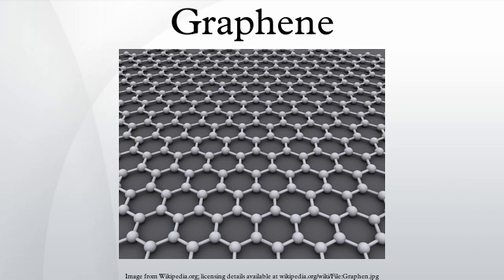Analysis of SLGO generated by this route reveals that the system is unstable, and room temperature stirring with HCl leads to around 60% loss of COOH functionality. Room temperature treatment of SLGO with carbodiimides leads to the collapse of the individual sheets into star-like clusters that exhibited poor subsequent reactivity with amines. It is apparent that conventional chemical treatment of carboxylic groups on SLGO generates morphological changes of individual sheets that leads to a reduction in chemical reactivity, which may potentially limit their use in composite synthesis.